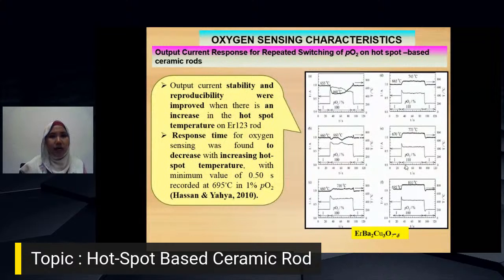Okay. Next, for the oxygen sensing characteristic, we have another material, which is a rare earth barium cuprate, but now you have erbium substituted on the rare earth element. You can see the oxygen sensing characteristic, and now I'm focusing on the output current response for the repeated switching of the concentration of the oxygen. The oxygen partial pressure is switched between 1% and 100% of the oxygen concentration in the surrounding.